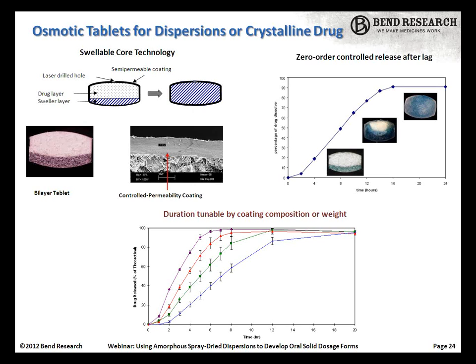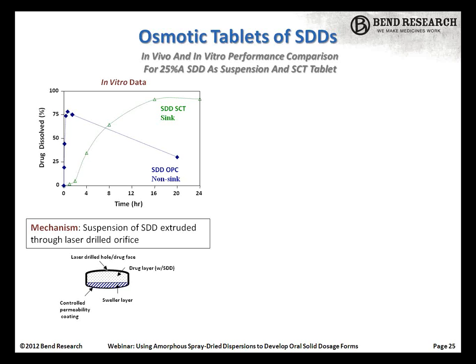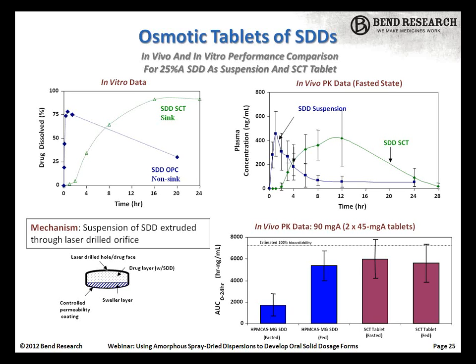Also, we can take these spray-dried dispersions. Okay, we had the animation on there, I didn't realize. So here we're just showing the spray-dried dispersion in the tablet. Well, this is the in vivo result from that. On the left-hand side is the in vitro on top. On the right are the in vivo results, and of course we're seeing the modified release. As is typical with an osmotic system, there is a lag period associated with the activation of the dosage form. In this particular case, the fed-fasted effect was mitigated by using this controlled release technology.